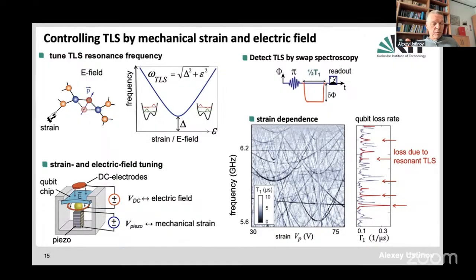The generic formula for the energy level separation for a double well potential is the square root of delta squared plus epsilon squared, where delta is the splitting in the symmetric well and epsilon is the asymmetry parameter of the potential. And you see all those curves resemble very much these hyperbolas, which could be flat or steep, well seen or not well seen, but all of them are really of this generic shape. Some of these hyperbolas end below the bottom of this plot because with this qubit of particular frequency we are only able to scan the frequency range in the range of about 20%. So some of them have frequencies well below that.